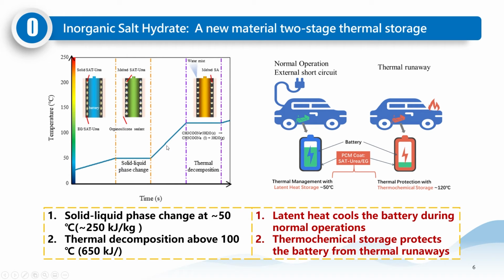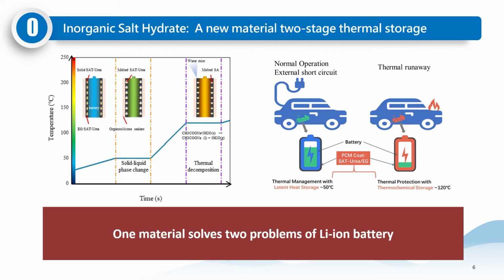What's more about this salt hydrate than the other PCM is that it has a thermochemical reaction at a temperature above 100 degrees C, with an energy density of about 650 kilojoules per kilogram. So with this salt hydrate, we can use it to cool down the battery when it is operating normally, or we use the thermochemical storage to protect the battery from thermal runaways when the temperature reaches above 120 degrees C. So we use just one material to solve the two problems of lithium-ion battery cooling.